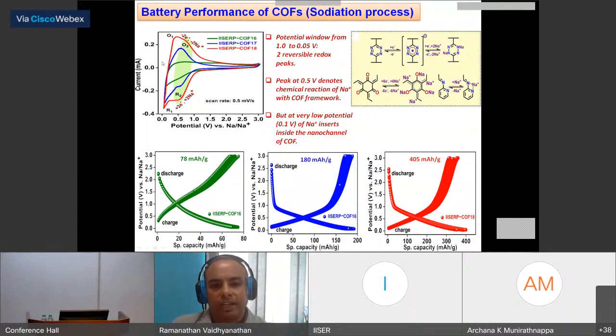As I told you before, because of the crystalline nature of the COF, we can calculate how many electrons are loading per unit, and we can also calculate how many sodium ions are loading per formula unit in this COF, which is excellent. And here are the charge-discharge curves of the sodium ion battery. What is important to see is that at a very small potential window of 1.0 volt to 0.05, you get all the redox activity happening. And this is very, very important for an anodic material, because now this helps you calculate the potential window at which you can operate a full cell in a comfortable manner when you combine it with a cathode like sodium cobalt.